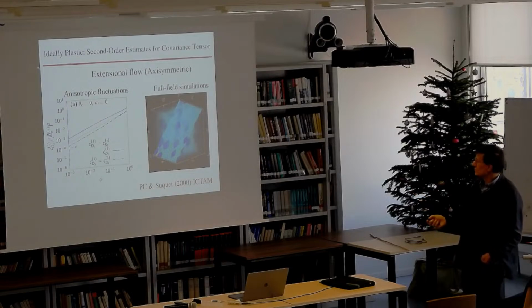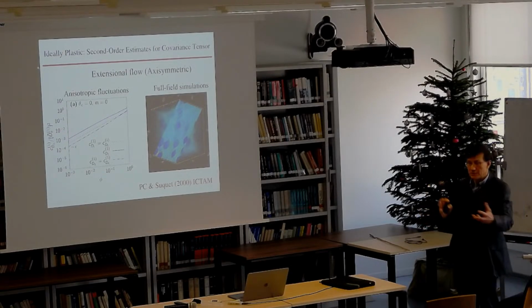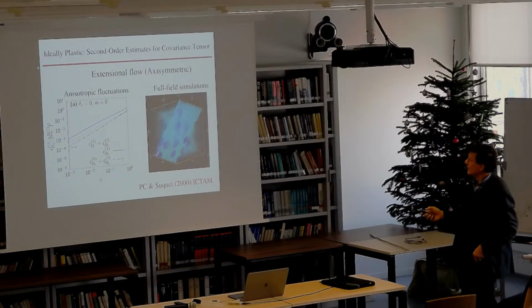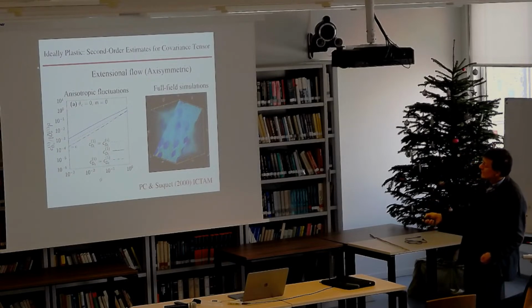I'll finish with these two plots that show the fluctuations in the strain rate as a function of the volume fraction. As the volume fraction goes down, in the axisymmetric situation, you get what you would expect—some slight anisotropy. These are different components of this fluctuation tensor, but they go down linearly in the volume fraction.